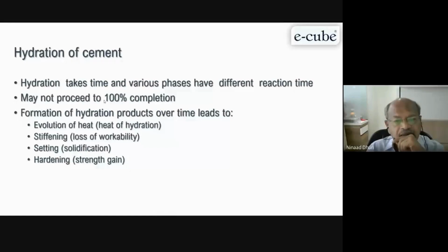So if you go into details and see under a microscope, you will understand, because we have studied in ACC the concrete strength development up to 10 years. And after 10 years, it was found that some of the cement had not yet hydrated 100%. Mainly they reach the level of 90 to 95%. So 5% unhydrated particles are available even after 10 years.